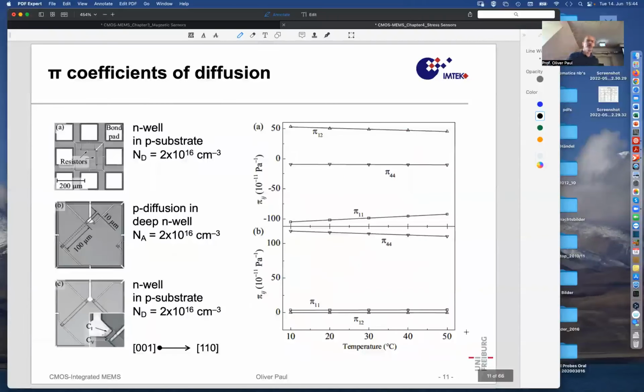And so, what are those coefficients? Here you see some values, and that's going to be the last slide of today's lecture. Measured values that we have measured with integrated piezoresistors diffused in commercial silicon. I think this was produced by X-FAB in a project, and you see N-well resistors in a P substrate with some nominal doping. You see P diffused resistors here in an N-well, and another N-well in a P substrate rotated under 45 degrees. This must be a 110 direction. This is to measure the shear coefficient of N material. This is to measure the longitudinal and transverse effect of N silicon, and this is to measure the pi11, pi12 coefficient of P silicon.